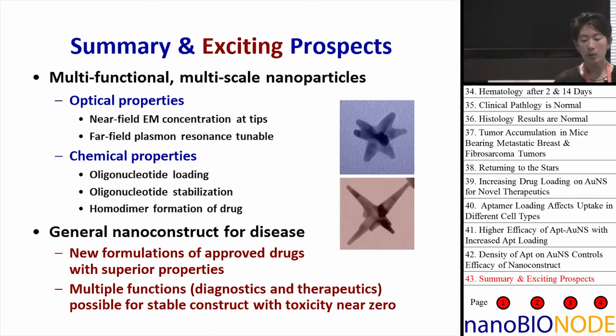So typically, what happens? So there are two situations. When we're doing these studies in vivo in animals, the vehicle is PBS, phosphate buffered saline, and so then you want to know within this buffer, what is the charge on the surface, and it's on the order of -8, -10 millivolts.